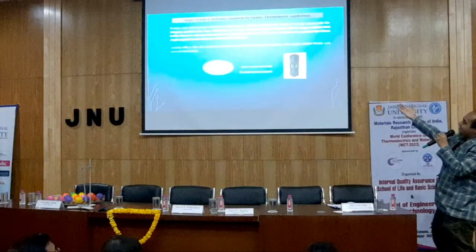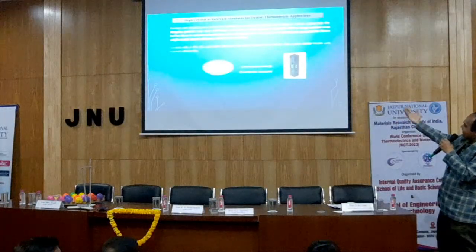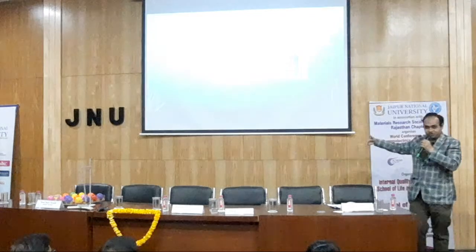The drawbacks are that powders or particles may have varying scattering or rapid aging due to large surface area, which I have highlighted. It will also lead to weighing inaccuracies and volume error. But if we go for a single crystal, like a thin plate of single crystal, it will give almost similar results with reduced uncertainty and can be used as a reference material for optical as well as thermoelectric applications, which I am going to highlight in the coming slides. And the approaches we worked on to get such crystals are either to go for a high-end technique or to modify the existing design so that we can get such crystals.